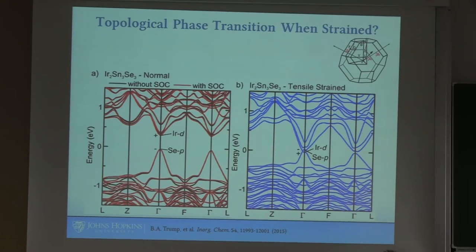It's got some magnetoresistance that we can't saturate with a 9 Tesla field. So you do band structure calculations on this material, and here's what we learn. This is the material with the lattice parameters as determined experimentally. Despite the very complicated structure, the band structure actually ends up with a single beautiful valence band here, poking out towards the Fermi level. And so, in fact, this is a p-type material, so it's the carrier density of holes of 2 times 10^19, and this is why. It's because even though it's got a complicated intrinsic structure, the result is actually a very simple band that looks pretty much like a simple semiconductor, and so that's why it behaves that way.